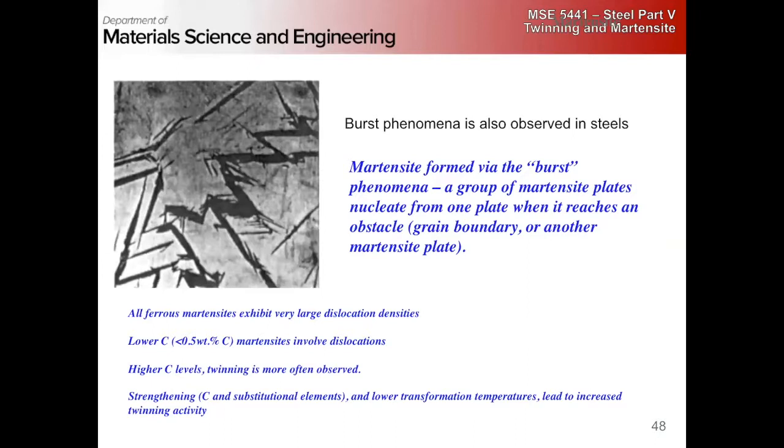It's a large amount of shear that needs to be accommodated by plastic deformation in the austenite, right? Those dislocations don't just necessarily go anywhere, right? So you've got plastic deformation happening in your whole structure, and those dislocations are still there after the shear, right? And so